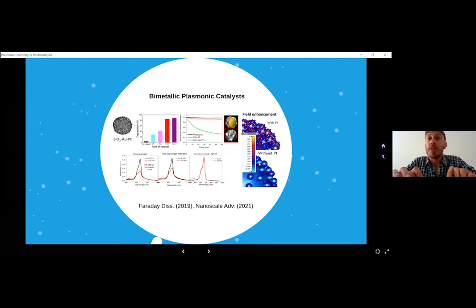And here you can clearly see, for example, from the field enhancement picture, what happens with these silica spheres with the gold nanoparticles, and what happens once you add these platinum clusters, right? So you can see here that the enhancement in the near field is huge when you add these really small platinum clusters, and they also behave much better towards the degradation of organic dyes when the platinum is present. And they explored all the different parameters that can affect the construction of this type of plasmonic catalyst.